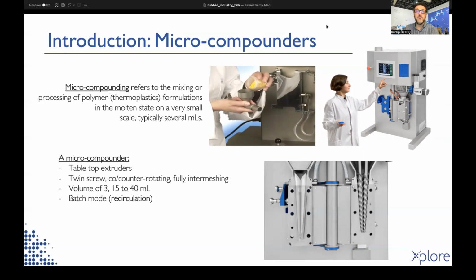Microcompounders are tabletop mini extruders having parallel twin screws, counter-rotating and fully intermeshing. The batch volume can be varied between 3 cc to 40 cc. The core of the compounder is a vertically positioned liquid-tight barrel with two easily detachable conical mixing screws. Both screws and housing are specially engineered to minimize wear and to resist chemicals in a wide range of temperature.